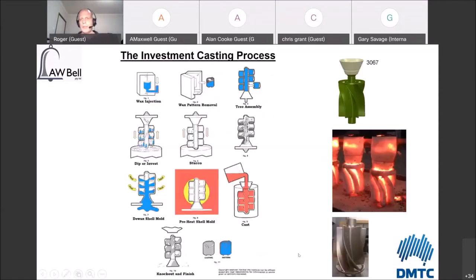So the investment casting process, I won't spend too much time on this because I'm assuming that most of the people here know a little bit about it. It's essentially the lost wax process where we start with injection of a wax part. We then take the wax component and put it onto a tree. We put a series of prime coat, backup coats and stucco onto the wax tree to produce a ceramic shell. After the ceramic shell is produced, we remove all the wax from it in an autoclaving process, preheat and fire the shell mold, cast metal into it, and then we have the tree that comes out.